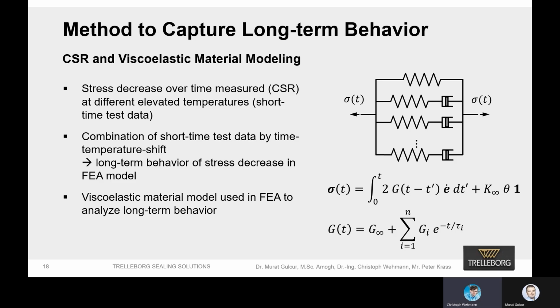You see some formulas at the bottom. The first one is the stress over time, the stress tensor, that's why it's written bold, and we have an integral because it's a history-dependent material law, so we integrate over time. You see the shear modulus, G, is a function of time, and it's multiplied by the strain rate, and then integrated. The strain rate, the small e, is only the deviatoric part of the strain, because elastomers mainly give their mechanical stress response due to the deviatoric strains. The volumetric part is on the right side, the K, the bulk modulus, and then the volumetric strain, theta.